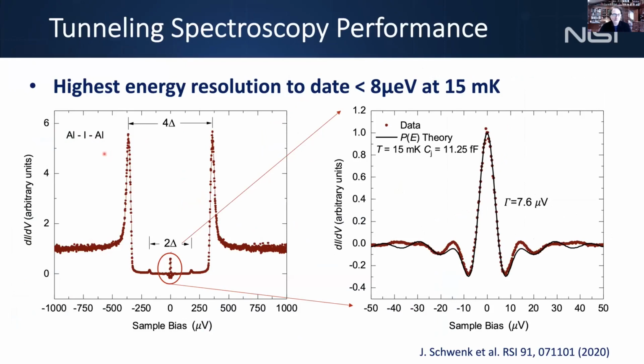The STM performance also got improved. This is a superconducting Josephson measurement with the aluminum tip and aluminum sample. If you look at the center peak here, the Josephson peak, this is on a microvolt scale, 50 microvolts. You can see we can resolve that to better than 10 microvolts. So now we have kind of the perfect instrument that can do high resolution STS, both near the base temperature of 10 to 15 millikelvin, and AFM measurements.